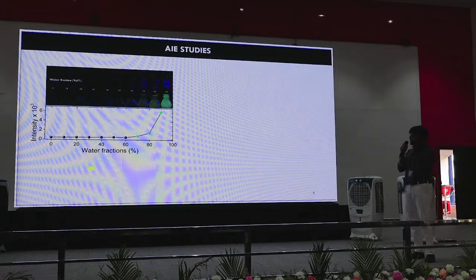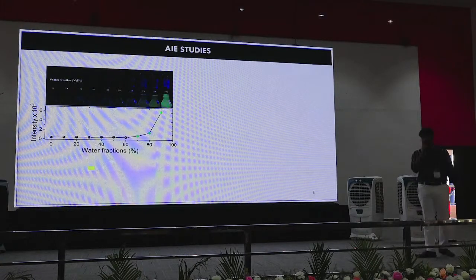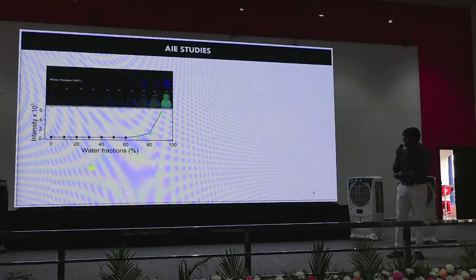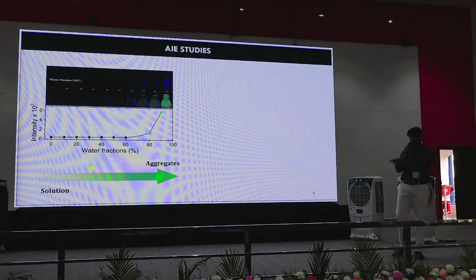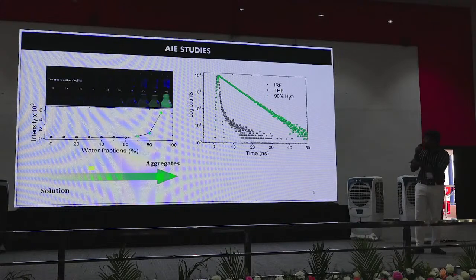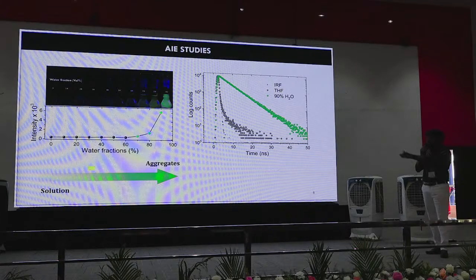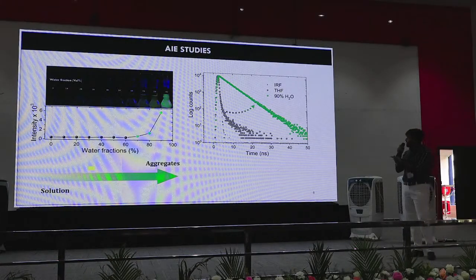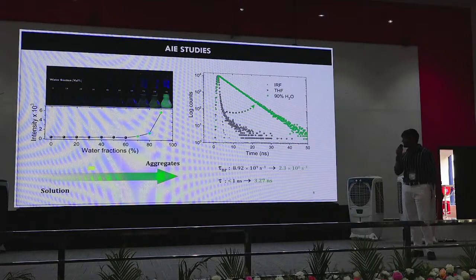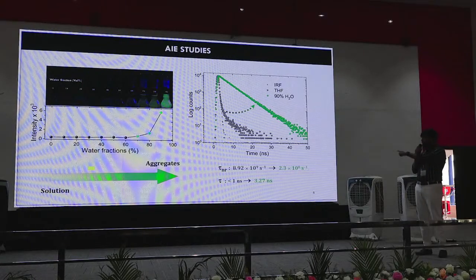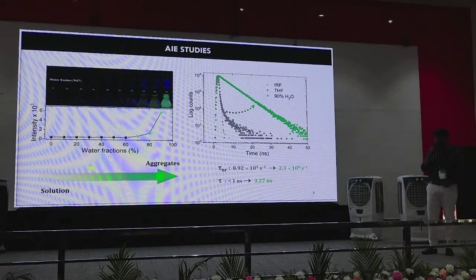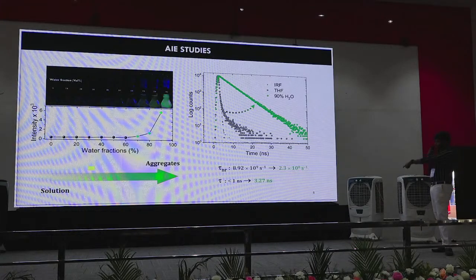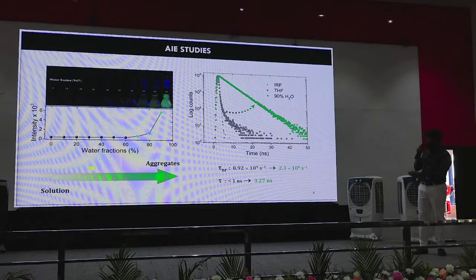Spectroscopically we have characterized this: at 90% water percentage, the fluorescence intensity is high. So when it changes from the solution state to the aggregate state, you can easily see that. We measured TCSPC, whereas in 0% water, that is in solution state, the lifetime is very poor. But in the 90% aggregated state, the lifetime is increased. Not only the lifetime is increased, but also the radiative and non-radiative decay has changed. Here the non-radiative decay, that is the rotation, is hindered, which is shown in the parameters itself. The non-radiative decay constant has been reduced.